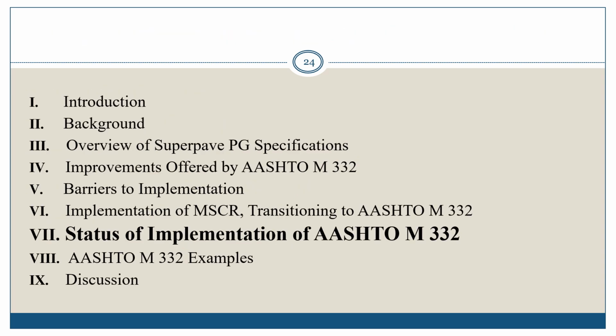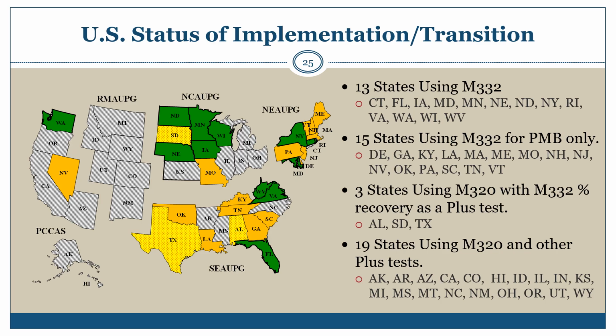Next, we'll have a quick overview of the status of implementation of AASHTO M332 in the U.S. As of the fourth quarter of 2019, implementation and transition to AASHTO M332 in the United States consisted of the following. 13 states are currently using AASHTO M332. 15 states are using AASHTO M332 for PMB only, for polymer modified binders only. 3 states are using AASHTO M320 with AASHTO M332 percent recovery as a plus test. 19 states are still using AASHTO M320 and other plus tests.